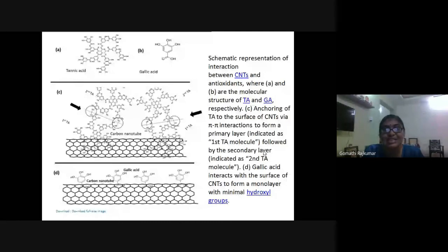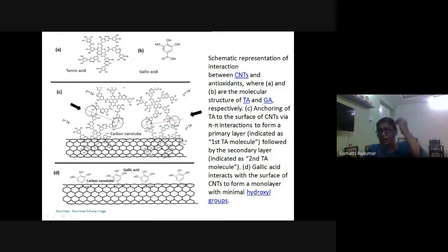So this is actually the schematic representation, which in short, I could tell you that this is the hypothesis that we gave out to the world. This is the interaction between CNTs and antioxidants, where here this is the structure of tannic acid and here this is the structure of gallic acid. Okay, this is the normal molecular structure of both these compounds. Now here you could see that this is a single wall carbon nanotube or multi-wall carbon nanotube, take anything for that matter. You could see anchoring of this tannic acid to the CNTs via pi-pi interaction.